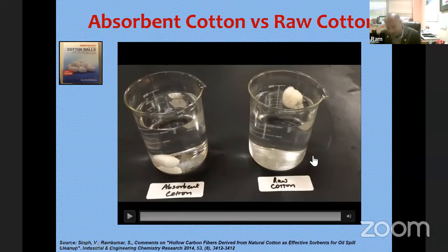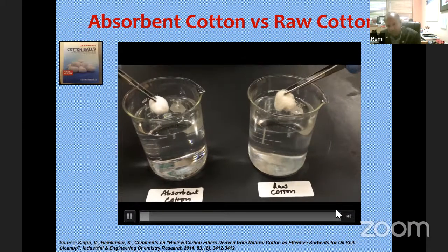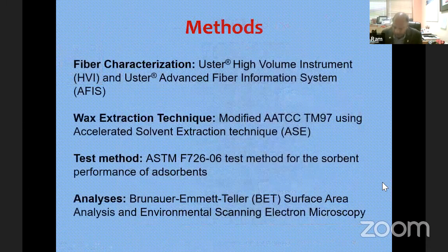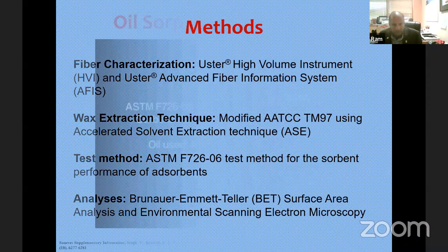Now I have proved that the low micronaire cotton will not sink. That is what we need because the oil comes on the surface of the ocean because of its density. So the material which we are putting to absorb should not sink. That I have proven. Now I have to establish one factor. I proved that if you take a low micronaire cotton, it is not going to absorb water. That is what we needed. And then it should only absorb oil. Now I have to prove results showing that it will not sink, which I have shown you by demo, but it will only absorb oil. That's what I'm going to do.